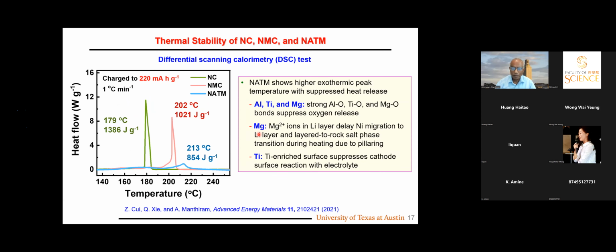Magnesium, when you have a small amount, goes to the lithium layer. So it can act as a pillar. So it can delay the layer to rock salt phase transformation. Titanium is on the surface, so that can help to have a more stable surface against the liquid electrolyte.